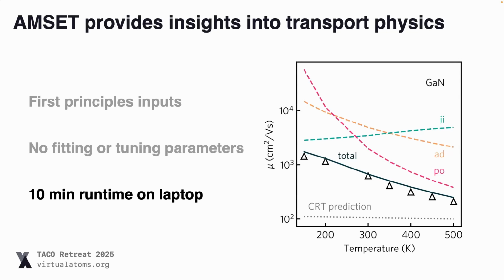So this is just some results for gallium nitride. The black triangles, those are the experimental results. The black line is the total result from AMSET. And I should say that this was obtained once we have all the materials properties calculated from DFT. This took about 10 minutes to run on my laptop, so it's very, very quick. What's nice is that, and again, I should say this is fully first principles inputs. There's no fitting or tuning parameters here at all.